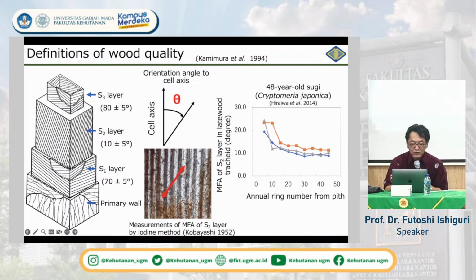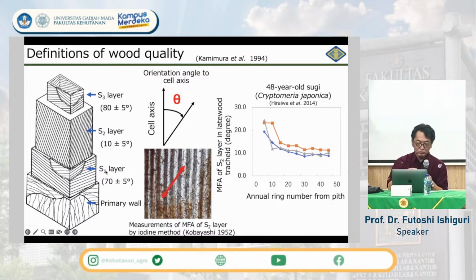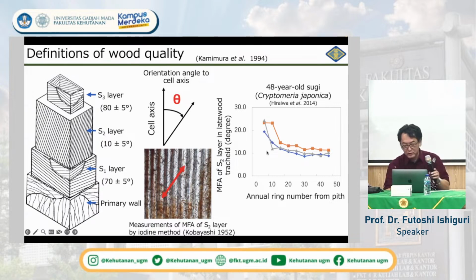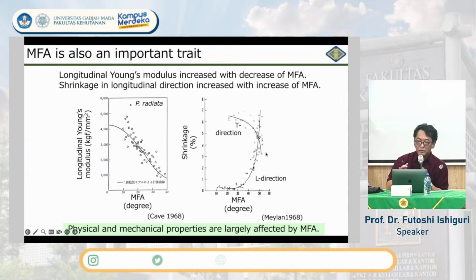And next is the microfibril angle. This is also very important. The cell wall has layers, and the thickest layer is the S2 layer, and we determine the microfibril angles of these layers. Usually the pith side shows a higher value of the microfibril angle, which dramatically decreases and then becomes stable around 10 degrees or less than 10 degrees. And the microfibril angle is quite important for wood quality.